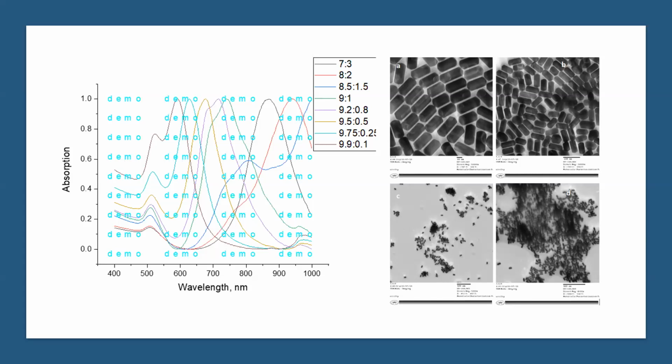From the repeated trial, we see the peaks were consistent and showed nanorods around 780 nanometer, but most of them were not able to show reaction advance, so they were not able to be normalized. Nonetheless, 9.9 milliliter of CTAB ratio with the 0.1 seedless gold nanorods has a full width half maximum of 98 nanometer, which was normalized correctly and shown uniformity.